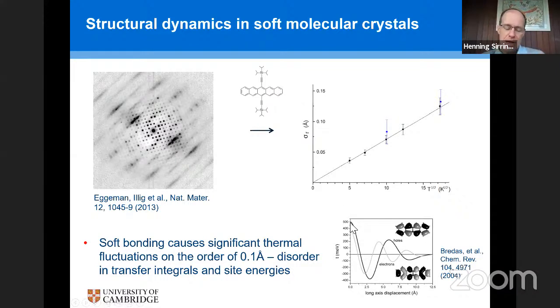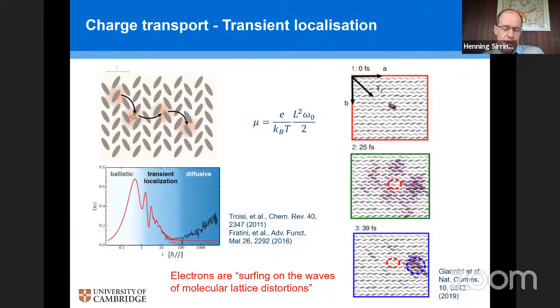So if you imagine now that in a solid system at room temperature the molecules are all vibrating with a few tenths of an angstrom amplitude, this means essentially that all the transfer integrals are fluctuating strongly with those molecular vibrations. And it's this dynamic disorder in the transfer integrals that is the key to understanding the transport physics of these molecular systems. And based on this hypothesis, there's been a theoretical model developed for these molecular systems that's called transient localization theory.